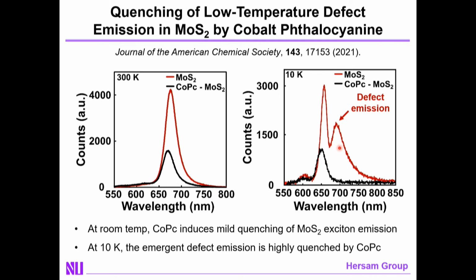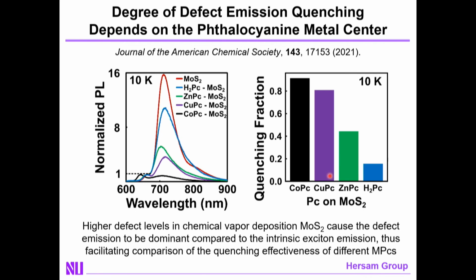And as you can see, when we deposit a 0D component on top, in this case cobalt phthalocyanine, we see very strong quenching, particularly of the defect emission. So this is a manner in which we can utilize a simple organic add layer to clean up the spectrum and enable you to use this material in a variety of applications, including quantum information sciences.